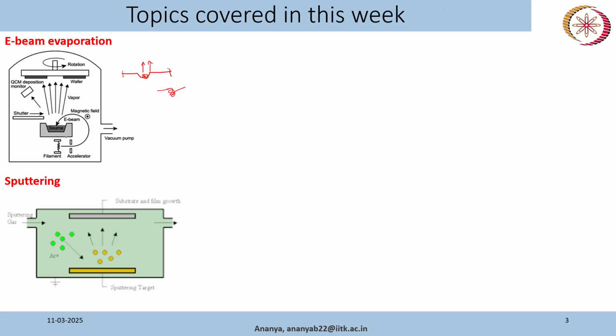Now here you can see this is kind of a boat or a crucible that holds our source material, the material that we want to deposit. So this can be of some material, say graphite. In the system we have in our lab, we use a graphite crucible to hold our material, and then we place our material here, and this electron beam locally hits this source. So we try to direct this electron beam, say, in the middle of our source.